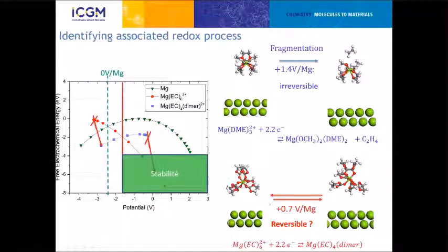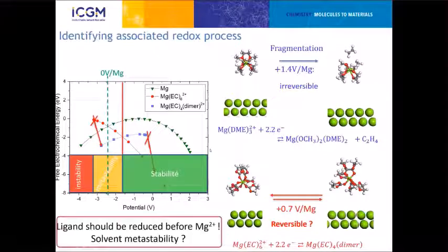So we can already define a stability domain where the solvent is going to be stable, but we have another domain where the solvents will be only metastable. We can find it, but it's not the most stable species. The most stable will be either the dimer or the decomposed DME molecules. And anyway, above a limit, there's no stability at all of the undimerized or unfragmented solvent. They will just become unstable. So there's a stability limit for these systems.